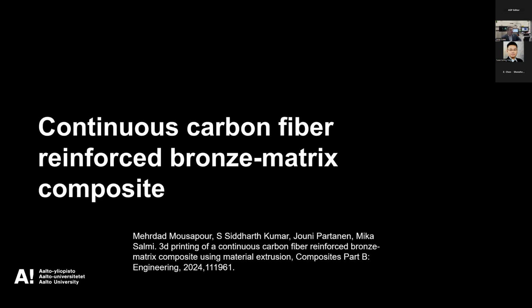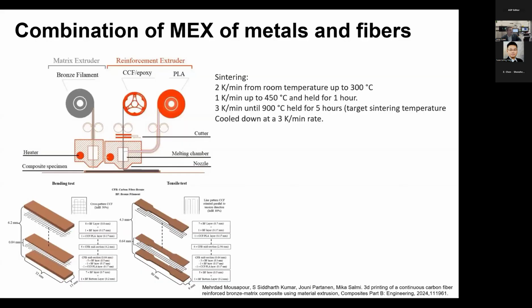Okay, then we could go to continuous carbon fiber reinforced bronze matrix composites. For this, we are again using a material extrusion printer, and again using carbon fibers there. But now our filament contains bronze, so it contains a lot of metal particles, and we can sinter them in our oven, and then we can have metal parts out from basically desktop printing with material extrusion.